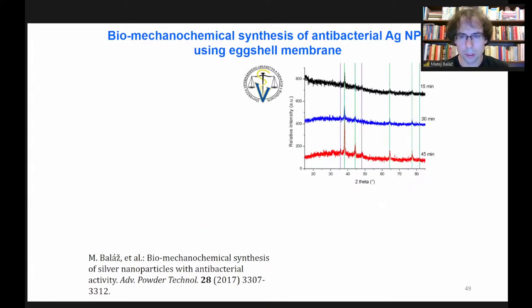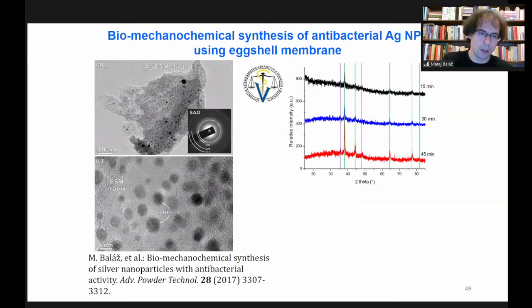One of the last examples I would like to show you is the synthesis of silver nanoparticles by using mechanochemistry. We introduced a process called biomechanochemical synthesis, where we performed a solid state reaction between silver nitrate and eggshell membrane. And eggshell membrane is a reducing agent. Here in the XRD patterns, you can see these green lines, they correspond to peaks of silver. Already after 15 minutes, we observed the reflections corresponding to it. But then, of course, as the time progressed, there was further increase. And quite nice nanoparticles, well distributed in this organic matrix, were found.